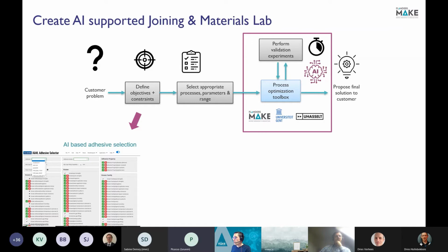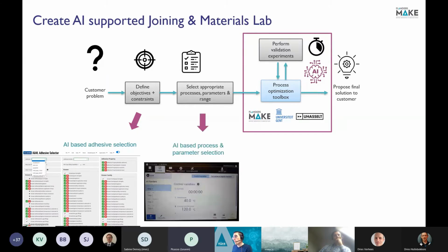So for example, if you tell it, okay, I need an adhesive with a strength of at least 10 megapascal, and it should work in a temperature range of 10 degrees Celsius till 40 degrees Celsius, for example, and I have other constraints, then this tool can look in a database of adhesives and use AI to suggest possible adhesives which can satisfy these conditions. And the other way around, you can also select an adhesive and then it can tell you, for example, the temperature range in which you can apply the adhesive or the timings, etc. We're also applying this tool for a second approach where we want to select appropriate processes, parameters, and the range. So that's a similar one.